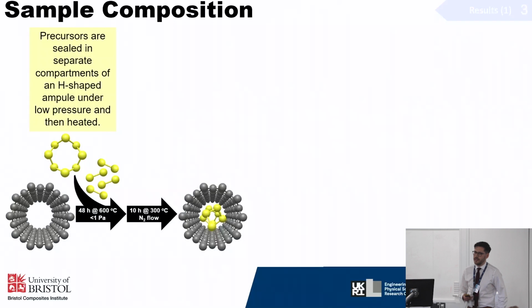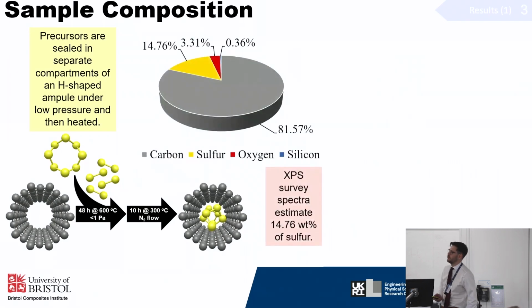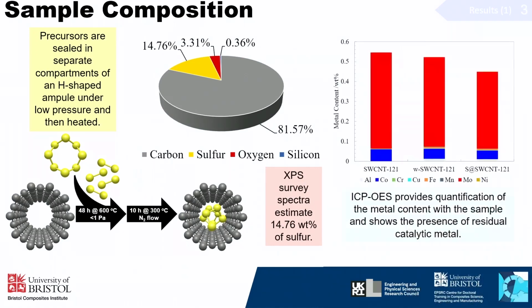So the particular sample I'm going to be talking to you about today is a carbon nanotube encapsulating a polymeric chain of sulfur. We've confirmed the presence of this polymeric chain through Raman spectroscopy and X-ray photoelectron spectroscopy. Using XPS, we can also get a composition of our material, and we can see there's about 15% weight of sulfur inside our composite.